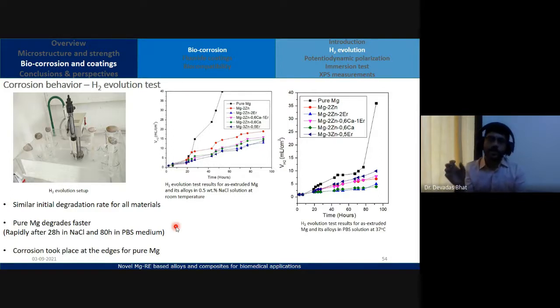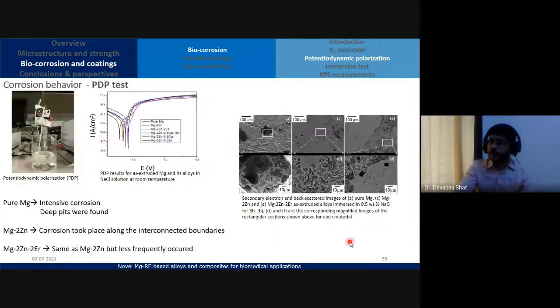How much hydrogen is evolved? Depending upon the stoichiometry, you can come to a conclusion that this much magnesium has got corroded. Okay, so here you can see for pure magnesium, we could see a rapid dissolution, whereas we had certain controlled degradation for the alloys. We performed this in sodium chloride and also in PBS.